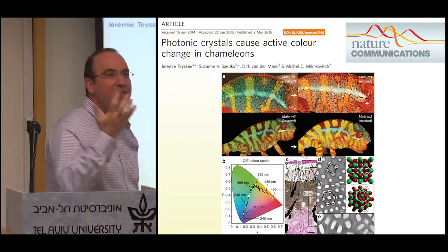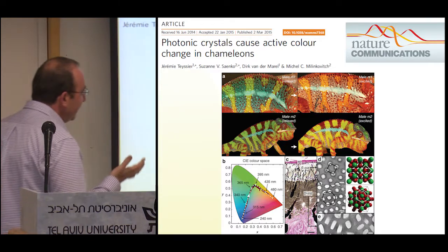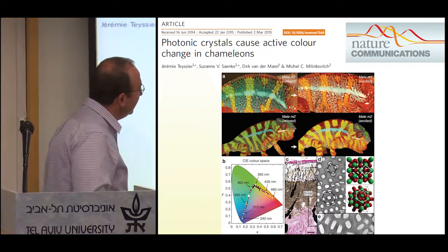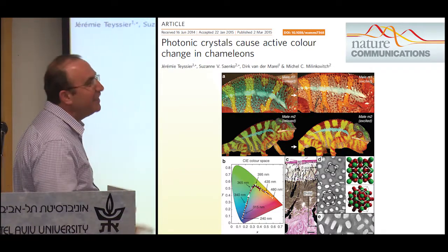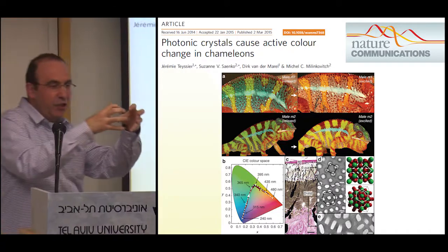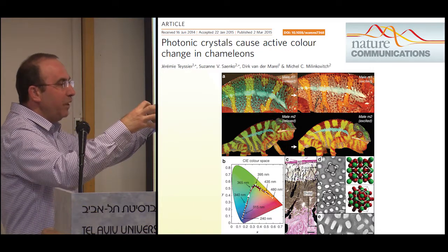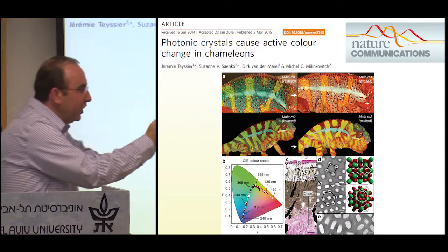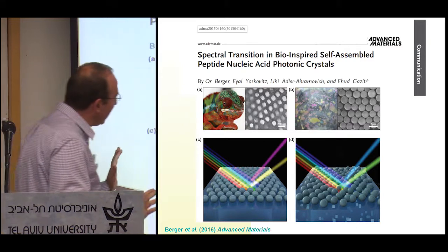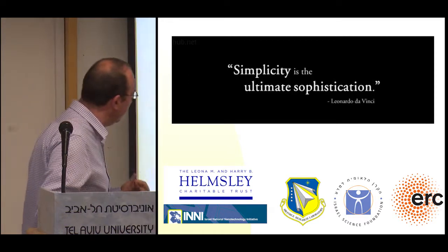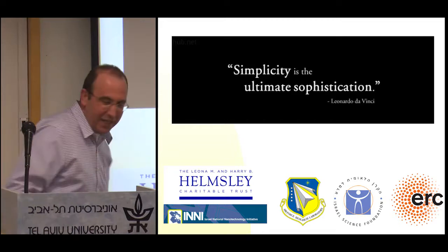finding the mechanism which I mentioned in the beginning for the color change in chameleons. So the same nucleobase, G structure, guanine that I mentioned, that we found in a systematic reductionist non-biased way is used by nature, by the chameleons, to make the color. These structures are charged, so you have a repulsion between them. If you put more salt, it masks the charge, so they are getting closer. And without getting anywhere into the physics or chemistry, we can do something like an artificial chameleon, and actually we are now getting funding from this, from the US Air Force Research Laboratory and others.